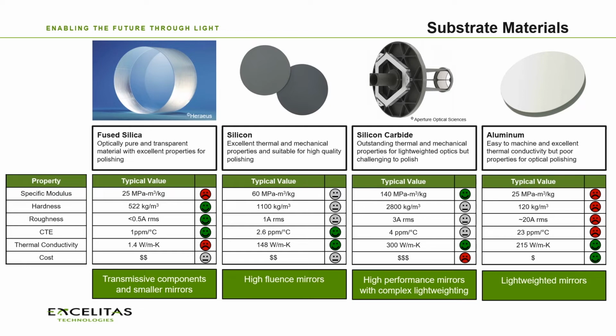Silicon carbide kind of represents the ultimate in a few of those areas. In terms of the specific modulus, its stiffness relative to its density, its ability to perform as a light-weighted material in very demanding environments, it really is second to none for those applications. Its thermal conductivity is also outstanding, and this is really why it's valued for these particular applications. It's challenging to polish. It's a very hard material, which means it's costly to polish, but often for some of the most critical optics, that's a trade-off that's worth making. And so it's usually used in the larger optics or things that maybe are in motion or where the weight is a really key consideration.